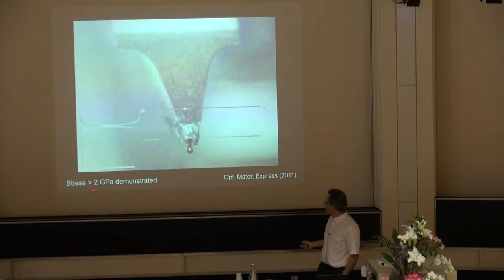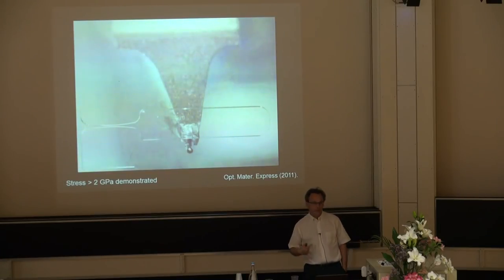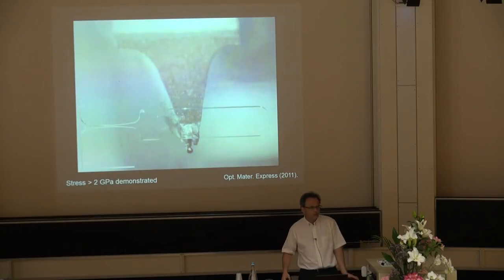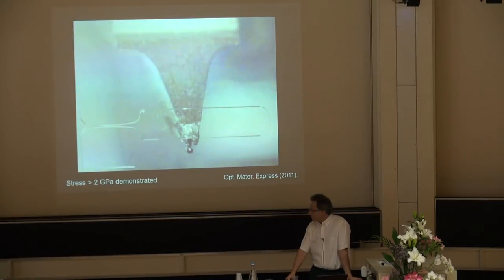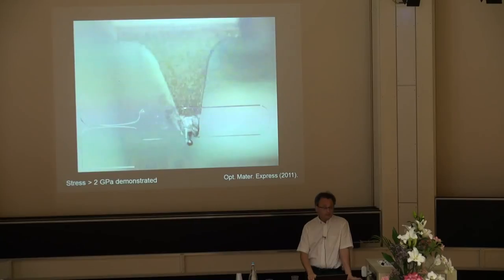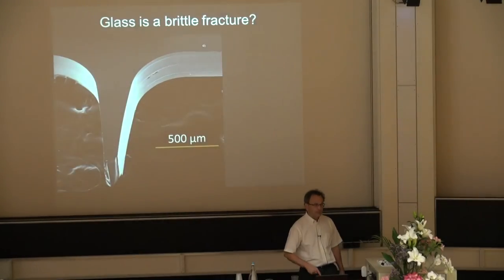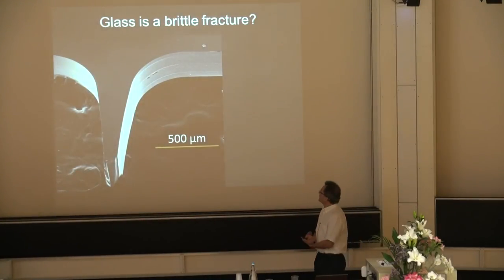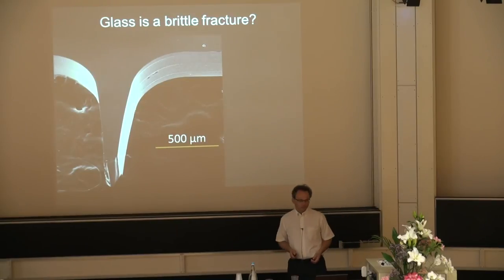So that's the reason why you get very easily up to 2 gigapascal or even more stress in the material. So it's more than steel, okay? It's way more. And a big difference with silicon, for instance, is that, again, this is an isotropic material. So it doesn't matter in which direction I'm looking. It will have the same properties. Okay? So glass does not flow. So we can do that, repeat that many times, and so on. Okay, now, eventually you can break it, okay, if you push it hard enough.